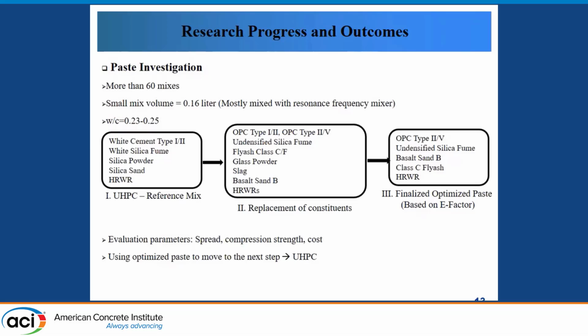We started with our house UHPC mix as a reference mix using white cement, white silica fume, silica powder, silica sand, and high range water reducer. Then we replaced several material constituents one at a time. For example, changing the type of cement, type of supplemental materials, which includes fly ash, glass powder, slag, and switching to basalt aggregates. Those are locally available here in New England area. We have analyzed those results and based on the E factor, which takes account of compressive strength, workability, and cost, an optimized mix has been finalized.